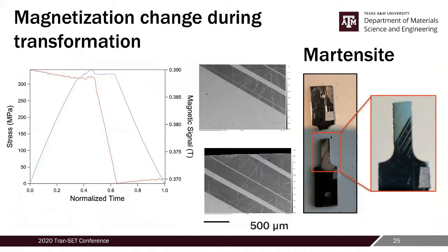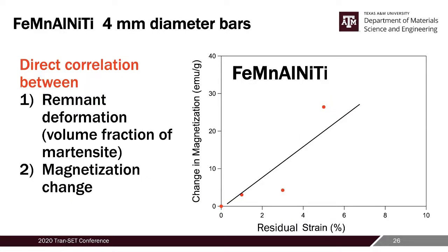response. And again, the blue line represents the stress. The red line here represents the magnetic signal. As this material deforms, you get a change in the magnetic signal. And here you can see in this image that these lines represent martensite. So the single crystal alloy transformed to martensite as shown in these images. And again, we also established a direct correlation between remnant deformation and magnetization change in iron manganese aluminum nickel titanium alloys.